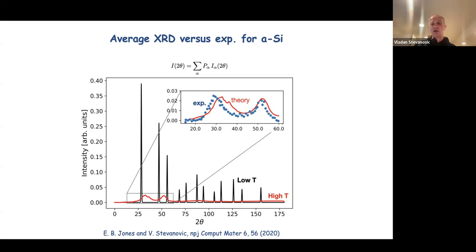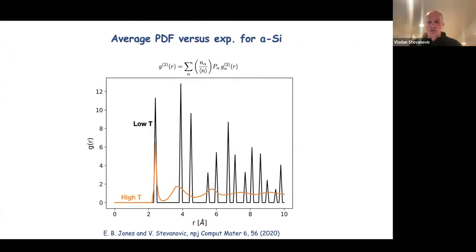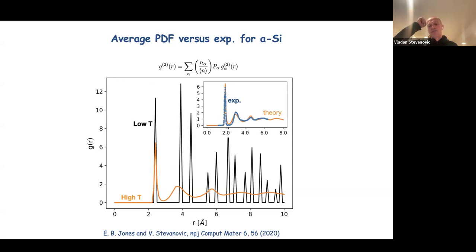And just to clarify this further, this has not been done as would usually be done on a large supercell. This has been done on a relatively large set of small cells, where each cell represents a local minimum obtained through this random structure sampling, followed by first principles relaxation, and then averaged. We can then go and average the short range order quantities. One of them is the PDF, the pair distribution function. Again, the low temperature average would resemble a crystalline phase, and the high temperature would be liquid-like or amorphous-like. Again, amorphous silicon experimental values correspond fairly well to what we predict.